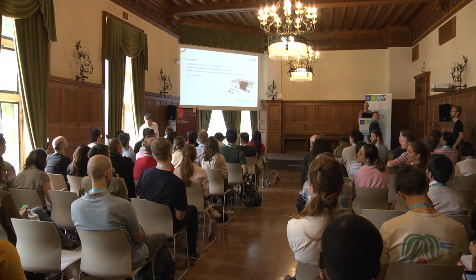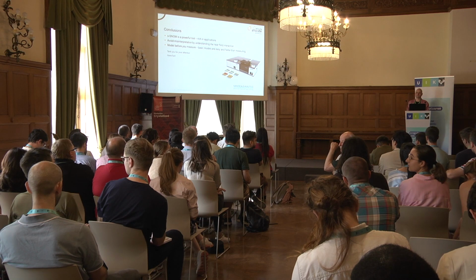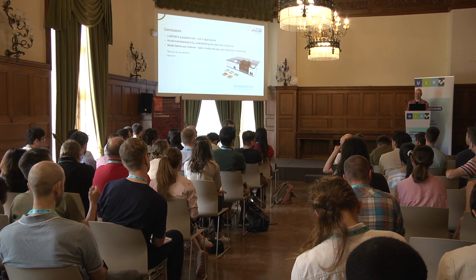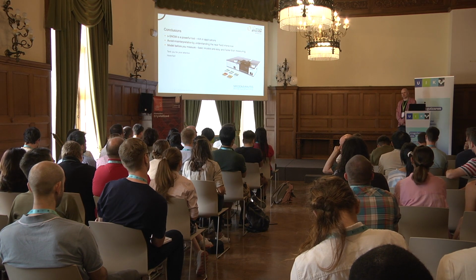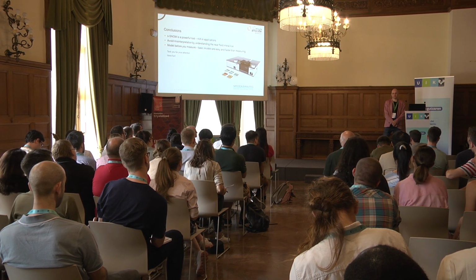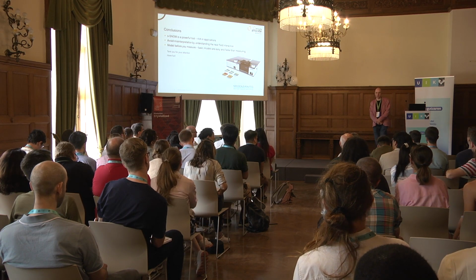Thank you. I have two questions. One thing about this finite dipole model, you have these two parameters which you find by comparing to experiments. Is there any wavelength dependence of these parameters, like length and G? Yes and no. It depends on the spectral range. If you go from IR to terahertz, then yes, there's a dependence. You need to adjust that. If you're interested only, let's say, in mid-infrared, then you can use one set of parameters and there's no dependence. You can neglect this. It's flat, more or less.